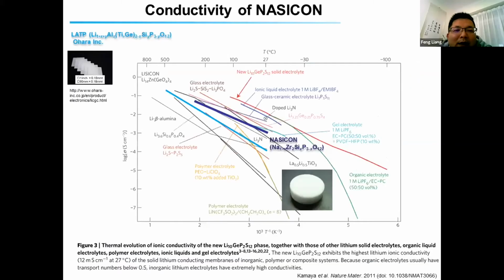And here I compared our NASICON structured solid electrolyte with the lithium-based solid-state electrolyte. So this is a LATP. As we know, this has been commercialized by the Ohara company in Japan. So our NASICON structured solid-state electrolyte has a higher ionic conductivity than the commercial case.